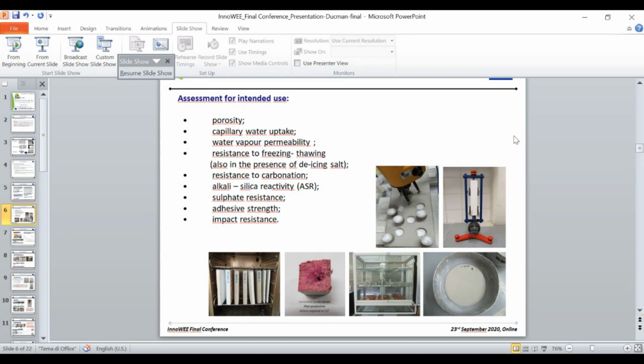So I will now present first results from the laboratory production and compare them later on with the results from the pilot production. The list of the selected tests is determination of porosity, capillary water uptake, water vapor permeability, resistance to freezing thawing, also in the presence of de-icing salt, resistance to carbonation, alkali-silica reactivity, sulfate resistance, and also bond strength and impact resistance.